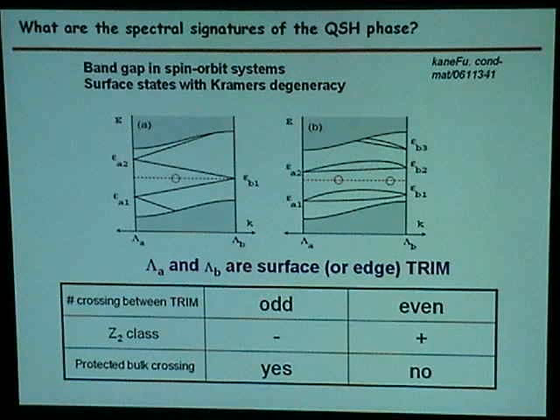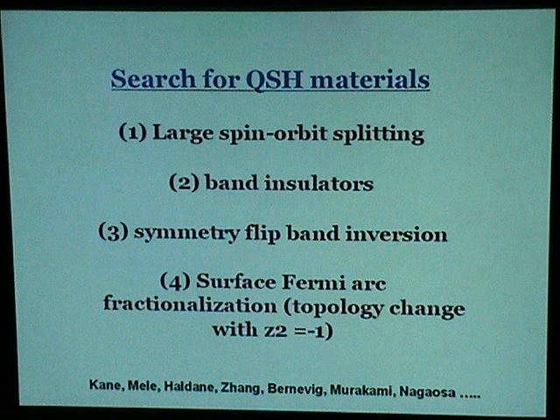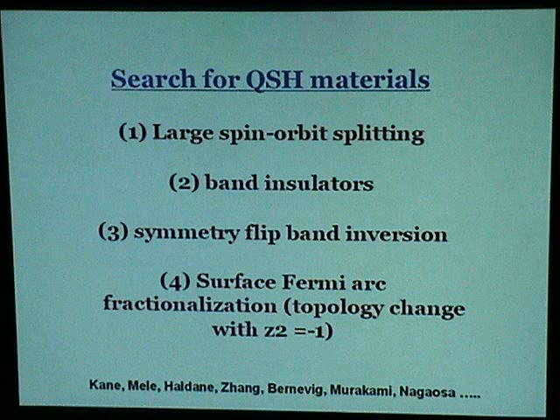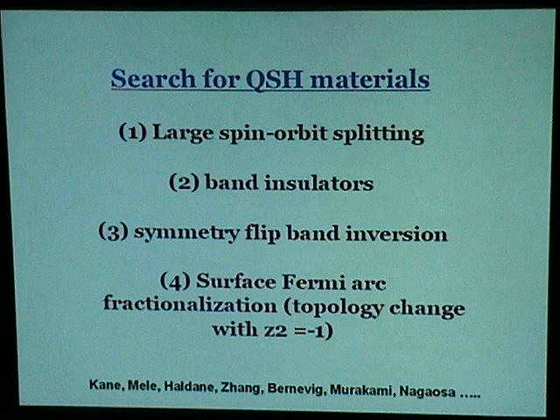What we have found is that there's a large spin-orbit splitting because, as Matthew pointed out, in the tight binding we fit with our bulk ARPES data, we need a large spin-orbit coupling to fit the data. So that confirms large spin-orbit coupling. Bismuth has large spin-orbit coupling from its atomic origin.